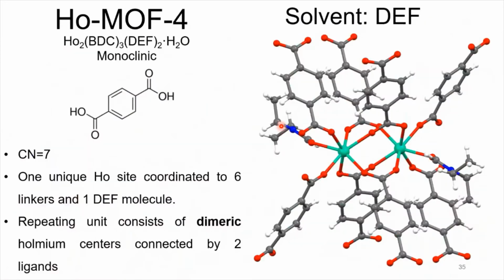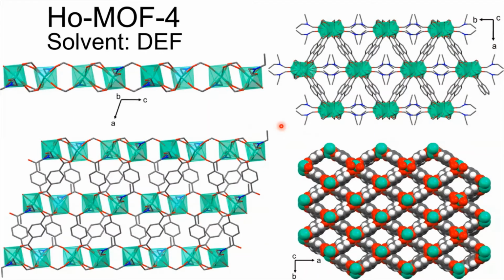And just to follow up on this, we changed it slightly. The solvent that we use, so DMF and DEF is literally just 1 carbon more in the solvent, and everything stays the same. Coordination number stays the same. Dimers, everything stays the same. And if you look at the structure, it almost looks exactly the same. The only thing is the pores do seem to be a little bit larger once the solvent is removed. So that tells us that the nature of the solvent really affects the final structure, but when you're dealing with similar solvents, they behave almost the same.